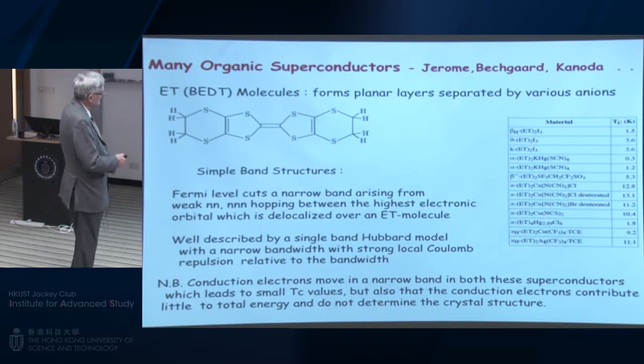And these are well described by a single band Hubbard model. That's a model where the interaction is localized on the site, and with a narrow bandwidth, because the overlap between these big states extended over the whole molecule to a neighboring molecule is small. So they move in a narrow band in both these superconductors with small Tc, so that the conduction electrons contribute little to the total energy, and they basically don't determine the crystal structure.